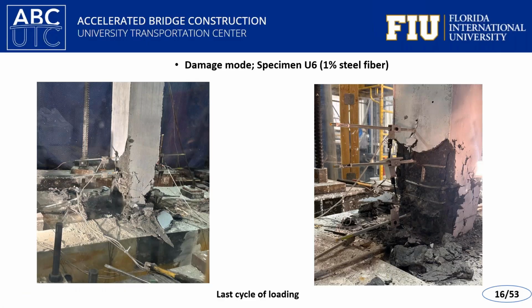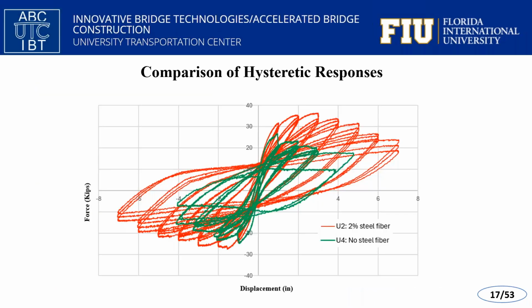This slide shows the damage mode observed in the last specimen, which had 1% steel fiber content. As seen in the image, the specimen exhibits multiple flexural cracks compared to the non-fiber specimen. The presence of steel fiber helps in bridging cracks, delaying the onset of major crushing and subsequently rebar buckling. The hysteretic response of specimens demonstrates the impact of steel fiber content on ductility, energy dissipation, and overall structural performance.